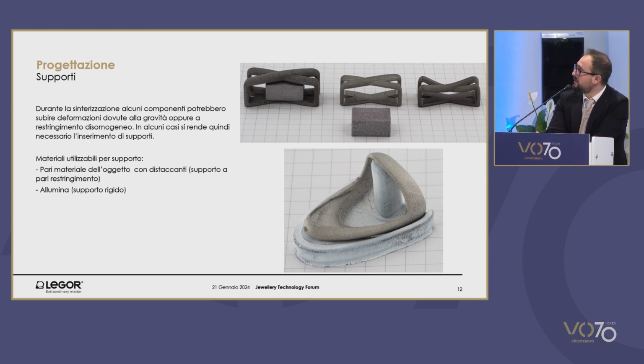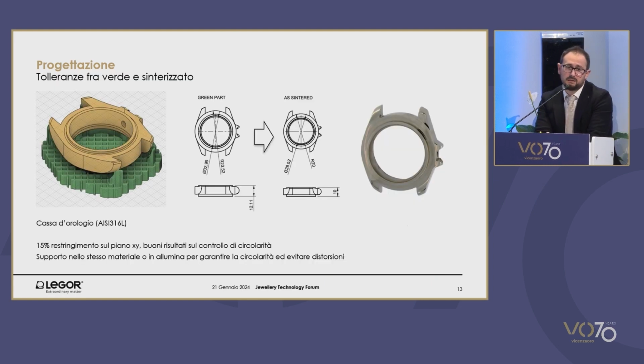In other cases, it is possible to co-produce both the item and the support. This has a meaning when we're talking about non-precious materials, but it becomes much more costly if you're using silver or other precious materials. Well, here the shrinkage phase that takes place during sintering allows me to have both the support and the item devoid of any tension that could take place when I have a base that has a certain friction and therefore prevents the upper part of the item from sliding, causing tension at the base that could also lead to distortions. So these are two amongst the many tricks that allow you to obtain complex forms, bearing in mind the thermal phase of the alloy.